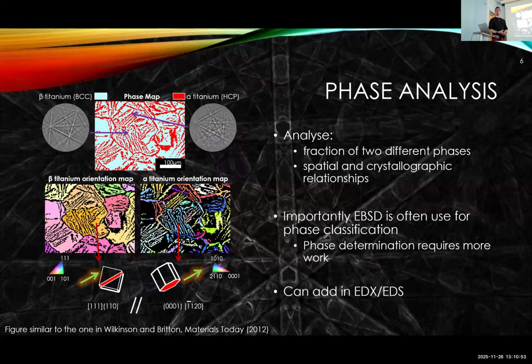And we see this beautiful microstructure appearing that we can now, within the software, pull apart to look at the microstructure of the beta phase, the microstructure of the alpha phase, and you can start to see orientation relationships inheriting between those two structures. It's a solid state phase transformation where the BCC high temperature phase transforms to a room temperature HCP phase, and you get inheritance of the basal plane to the 110 plane and the close packed a direction with the 111 direction in the BCC. And that controls things like how slip progresses through that system. That's super important to stopping airplanes breaking, which many of us like to fly occasionally, and we really like our planes to deliver people from A to B.